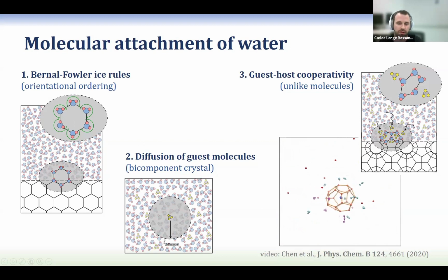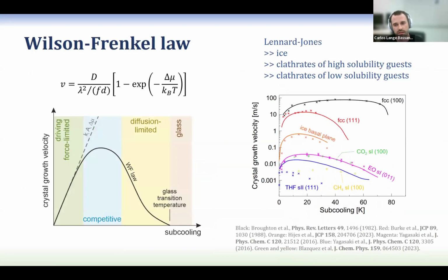So yeah, when we talk about clathrate hydrates, the mechanism of layer-by-layer growth is not the same anymore, right? So we need to consider all of that. And yeah, we can do molecular dynamics. They are not the most simple ones to do, but people do it. And we can generate these points here. Those are molecular dynamics simulations, sampling the crystalline growth velocity against the driving force.